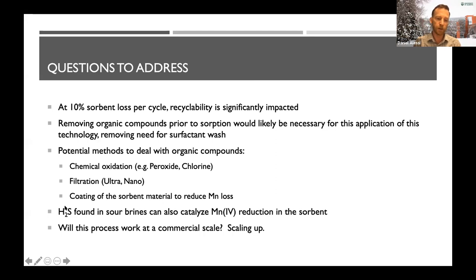And what I didn't talk about at all is H2S, the hydrogen sulfide or dissolved sulfide that's found in a lot of brines. Many brines are sour here in Alberta, and this does exactly the same thing. I won't repeat myself on that, but it very readily reduces manganese 4 to manganese 3 and 2. And the same thing, when the solid sees the acid, you dissolve your sorbent every single cycle. So hopefully this helps you on some of the problems we're facing. I think those are some of the big ones.